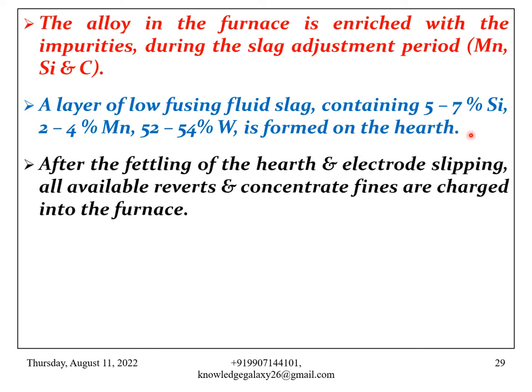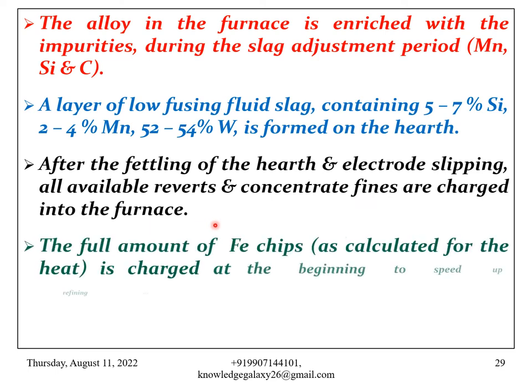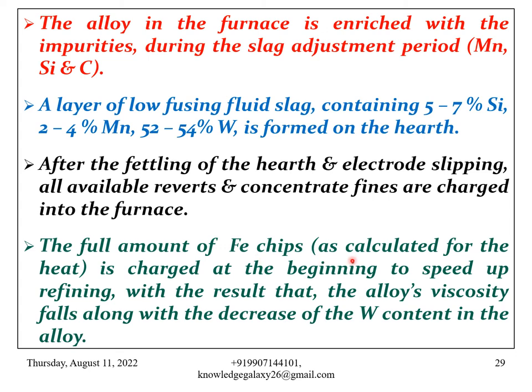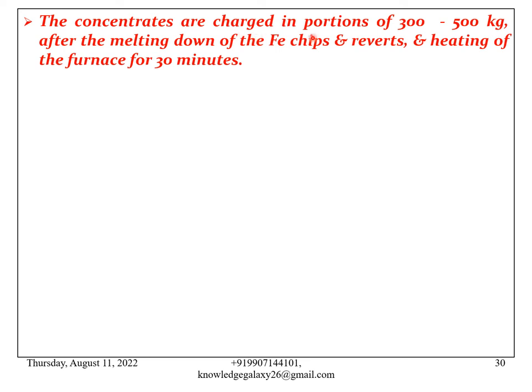After the fettling of the hearth and electrode slipping, all available reverts and concentrate fines are charged into the furnace. The full amount of iron chips, as calculated for the heat, is charged at the beginning to speed up refining, with the result that the alloy's viscosity falls along with the decrease of the tungsten content in the alloy. The concentrates are charged in portions of 300 to 500 kg.